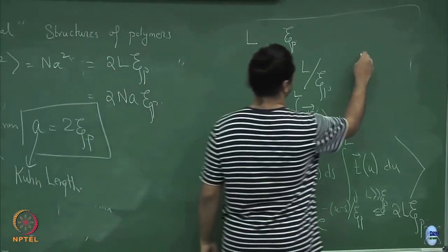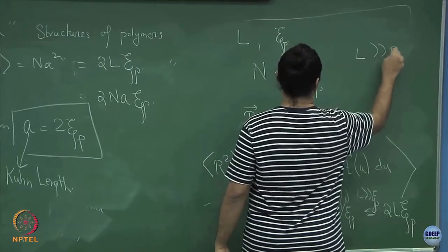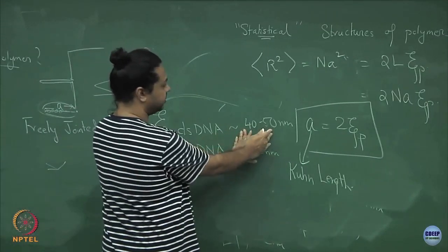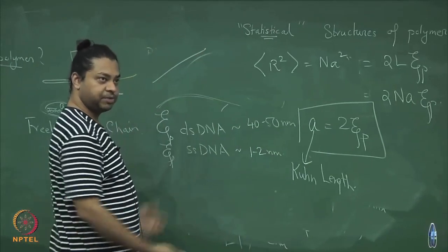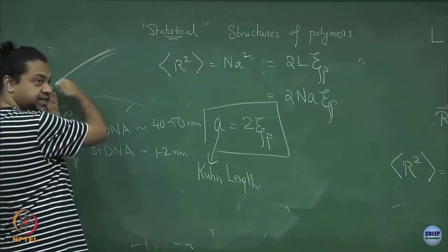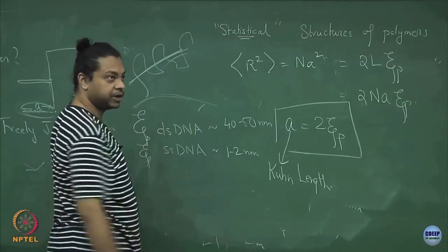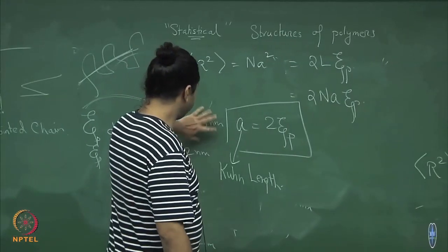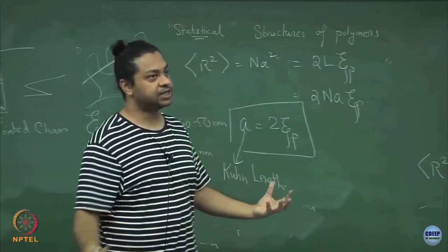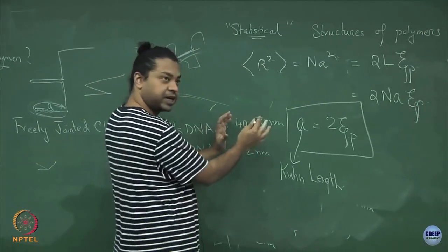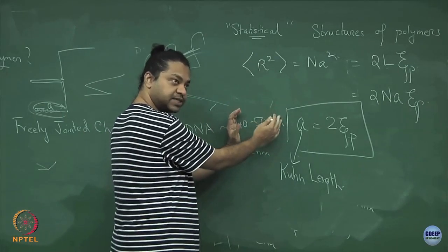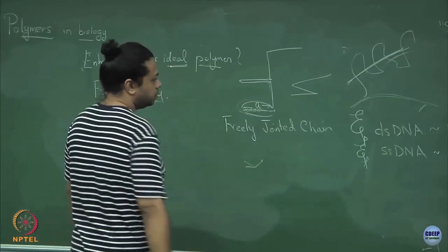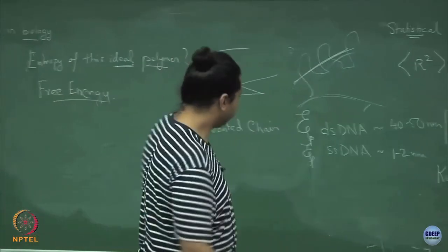If your total DNA strand length is of the order of the persistence length — say 50 or 100 nanometers — then the freely jointed chain theory is no longer valid, because the condition L >> ξ_p is violated. A DNA strand of 20 nanometers would look like a stiff rod, because it is much smaller than the persistence length and tangent-tangent correlations are strong. The theory you use to describe a polymer depends on what its persistence length is, which depends on the chemical structure.